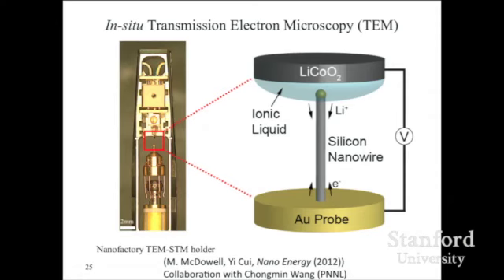You had some really nice in-situ TEM videos of your batteries charging and discharging. I'm just wondering how you deal with beam-induced damage in those experiments. So when we set up that in-situ TEM, you see that we intentionally avoid the electron beam hitting the organic electrolyte. You see right here, the reason we use this geometry is to insert the wires into the liquid, and the electron beam only looks at this. It doesn't damage this. If you look at the organic electrolyte, bad things happen very fast. But with that said, we still are careful, even though this is inorganic material. If you look at this with the high energy focused beam, you still induce certain changes right there. We can only take precautions, try to spread the beam, not to introduce much damage right there. Yeah, that's the only thing I can say.